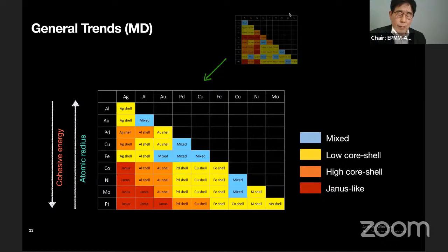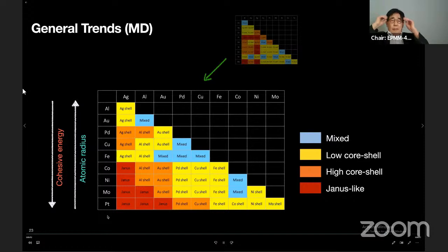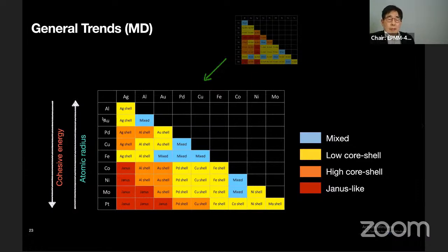So we could update the old table by reordering this sequence based on each material's cohesive energy and atomic radius. For example, platinum is the most core-preferring material among these metals we looked at, and this core preference decreases as we go up the table, and aluminum at the top is the most surface-preferring material among these. The table is nicely sequenced because we can see by just looking at the color distribution that the highly segregated structures are formed at this corner, and the mixed ones are at the diagonal.